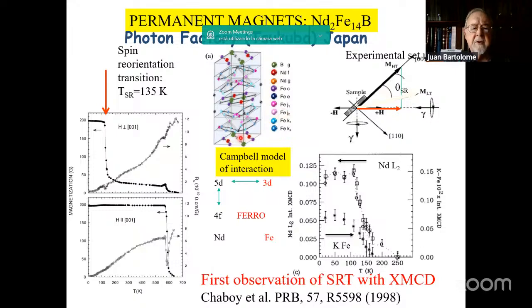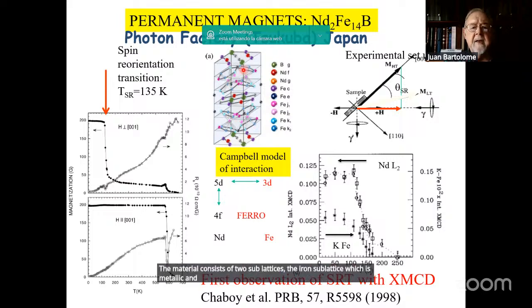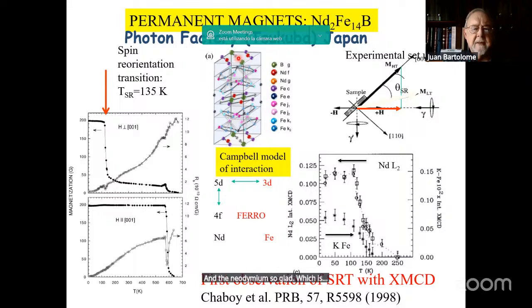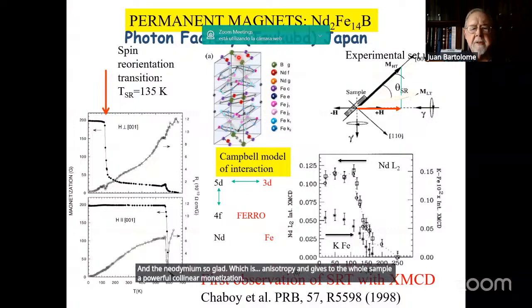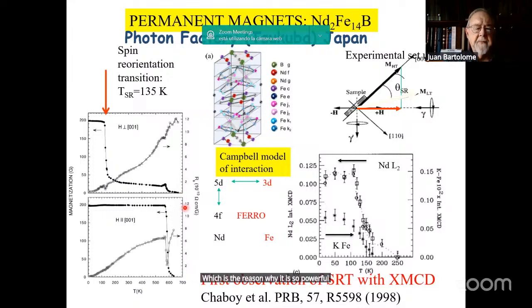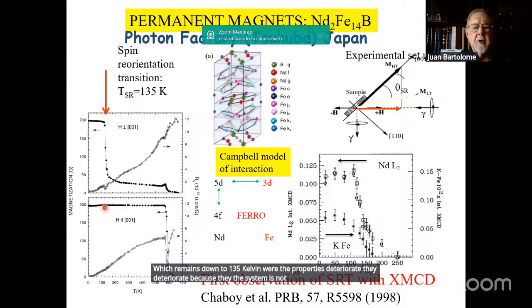The material consists of two sublattices, the iron sublattice, which is metallic, and creates a very large magnetic moment. And the neodymium sublattice, which has uniaxial anisotropy and gives to the whole sample a powerful collinear magnetization, which is the reason why it is so powerful. So below 588 Kelvin, you see here the magnetization, which remains down to 135 Kelvin, where the properties deteriorate. They deteriorate because the two sublattices are not anymore collinear. They are not oriented in the same direction.